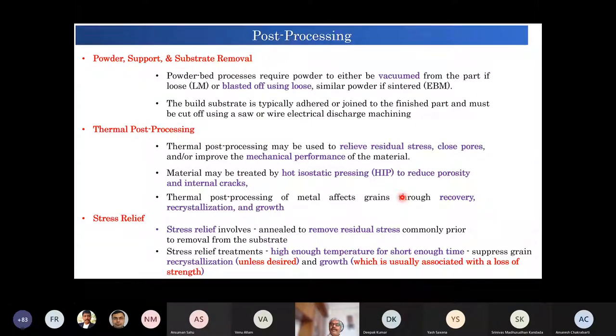Now, this is all that we get after processing. And then whether what we get after processing, with all kinds of limitations that I have mentioned, is suitable for use? Obviously no, because the processes are not optimized, because here the control over the process is lesser than a normal wrought process or casting, which we have been knowing for several decades. Even though casting is a slightly less controlled process, we know by now how to control the structure and properties of a cast material, and porosity. All these things are now well established because of the practice and the immense amount of research that has gone in. So the most important is post-processing, and the important stage that comes is the substrate removal, right?